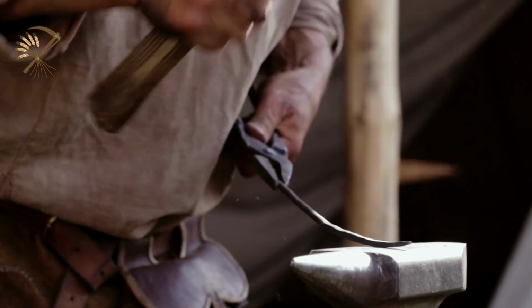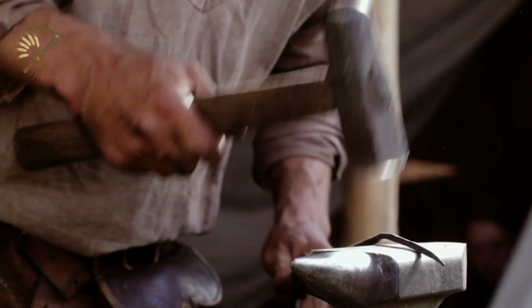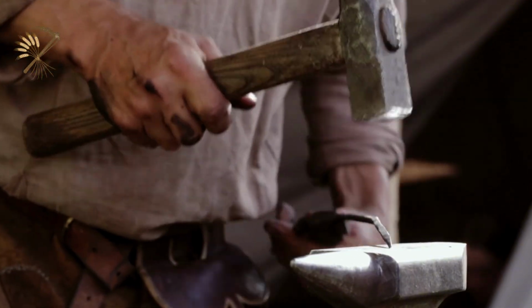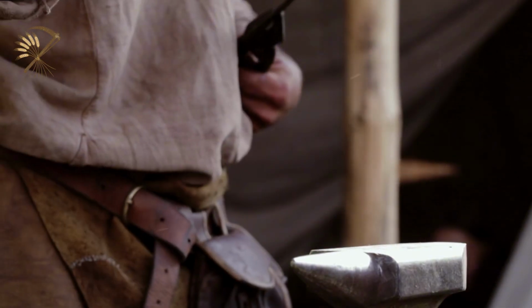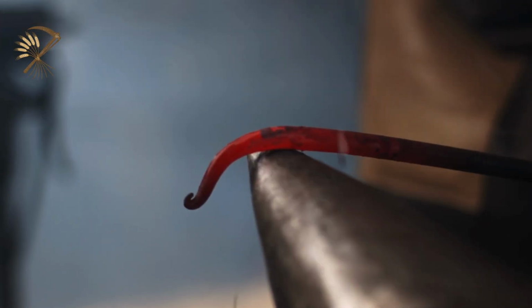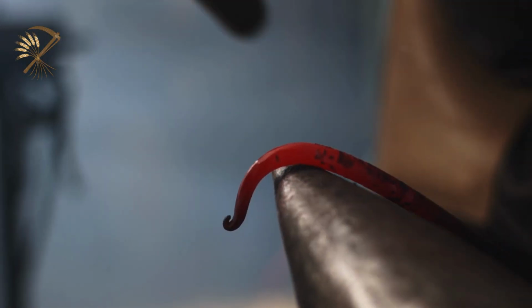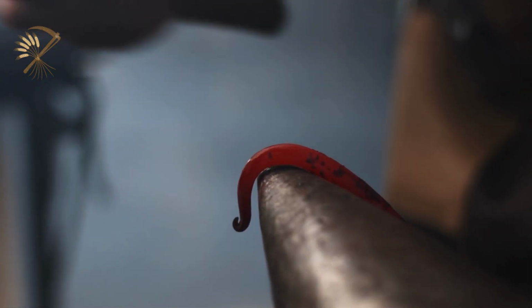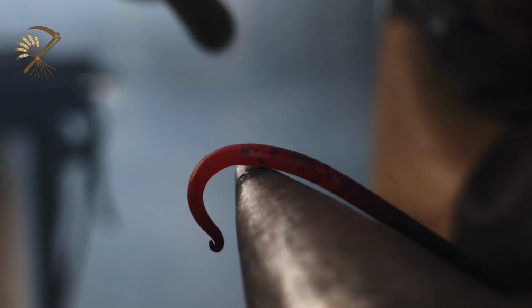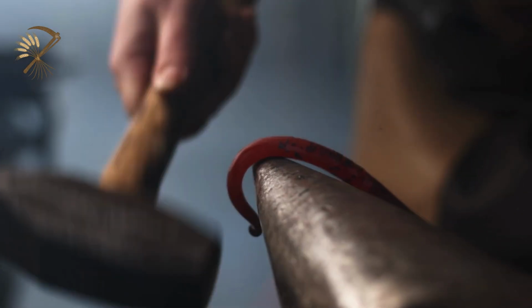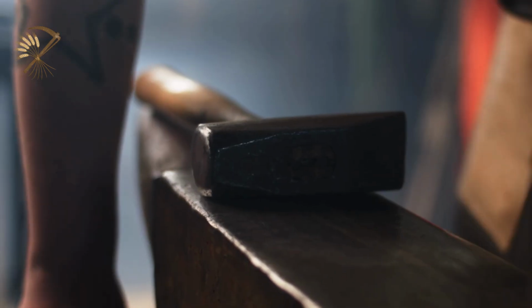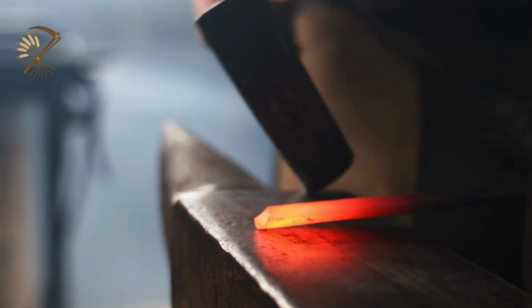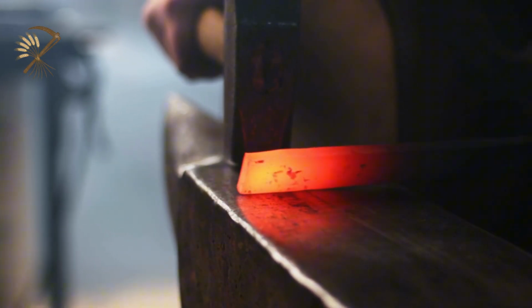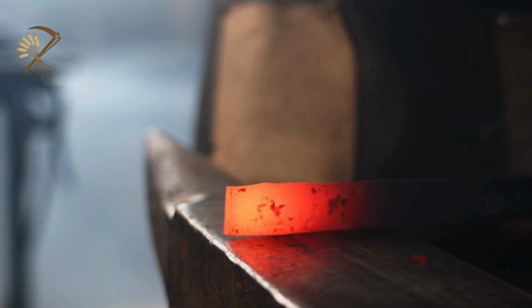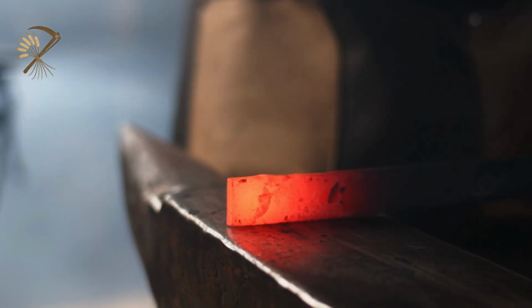Upsetting concentrates mass by hammering on the end of the piece, compressing it shorter and thicker. This technique is used when a tool needs extra material in a specific location, creating the eye of an axe head where the handle inserts, or thickening the cutting-edge zone before final shaping and grinding. The piece is held vertically with the end on the anvil and struck from above, or held horizontally and struck on the end. The total hammer blow count per tool reaches 200 to 500 individual strikes. Each blow delivers 15 to 25 pounds of force, meaning 3,000 to 12,500 pounds of cumulative force shapes each tool.